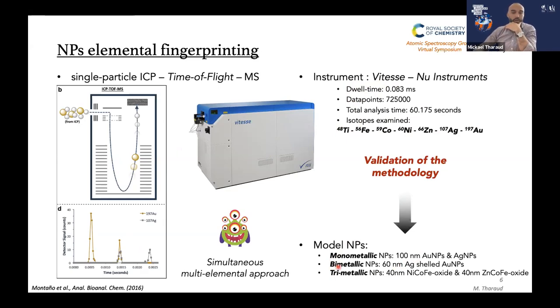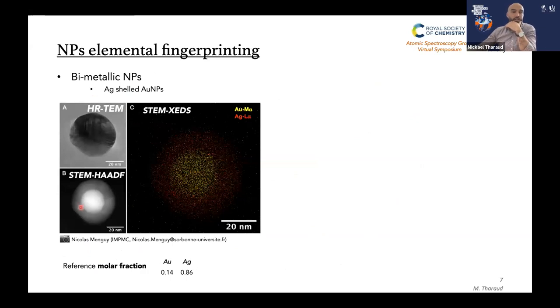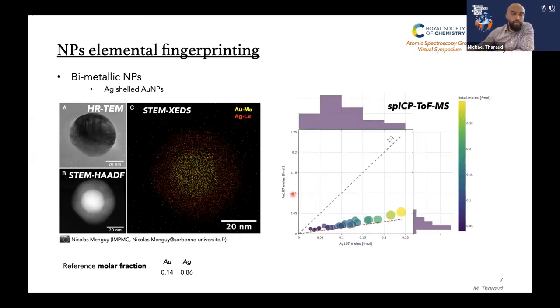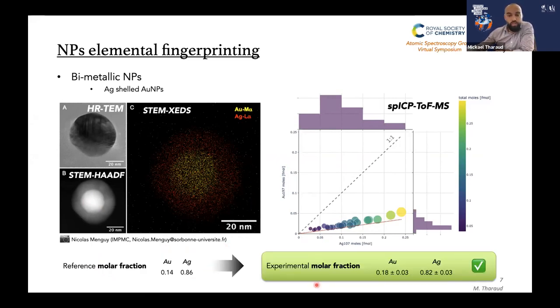And if we go directly for the results of the bimetallic particles, as you can see here on these TEM images, there is a core of gold and a shell of silver. And if we analyze a suspension of those nanoparticles using single particle ICP TOF-MS, and plot the number of moles of gold versus the number of moles of silver, we can see that the nanoparticle composition follows this nice line here, which is the reference molar fraction. And when we average the experimental molar fraction, we see that the results are in quite good agreement with the reference molar fraction.